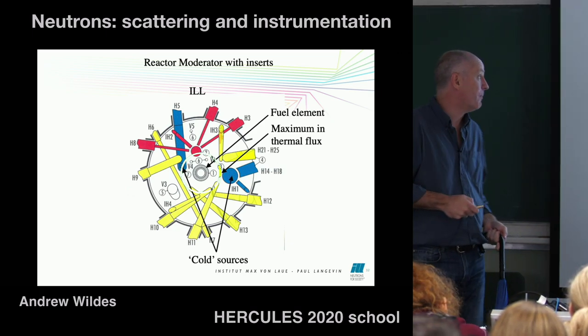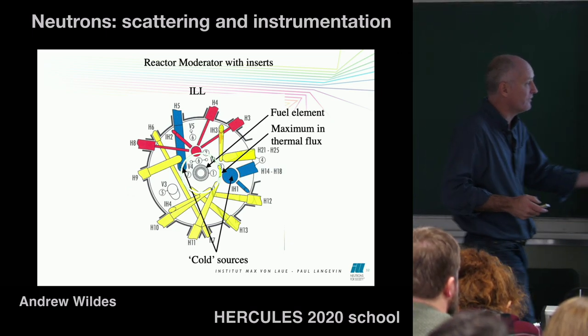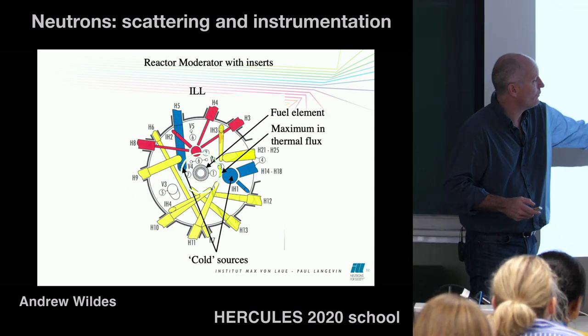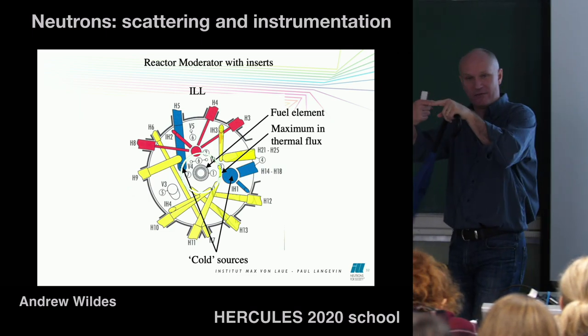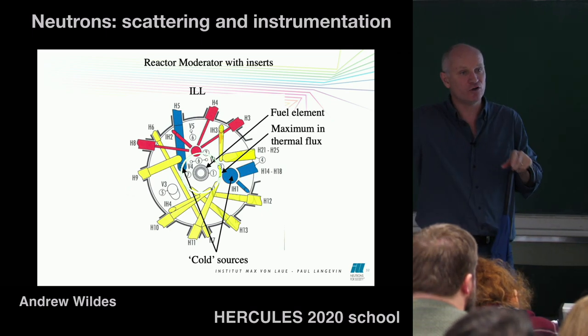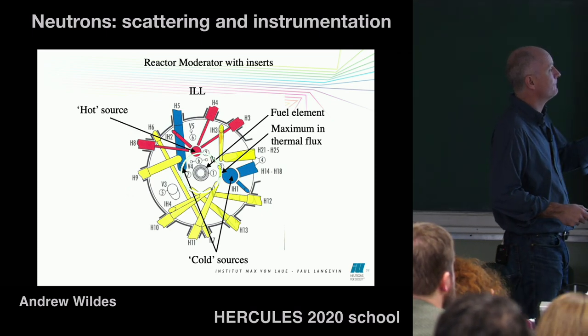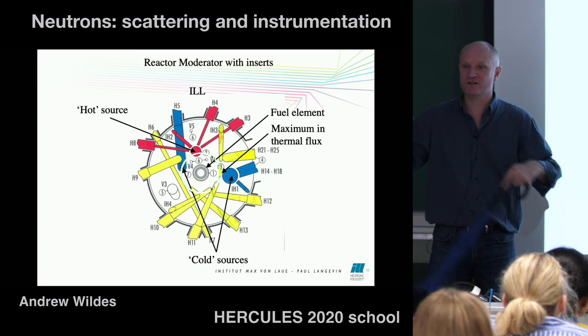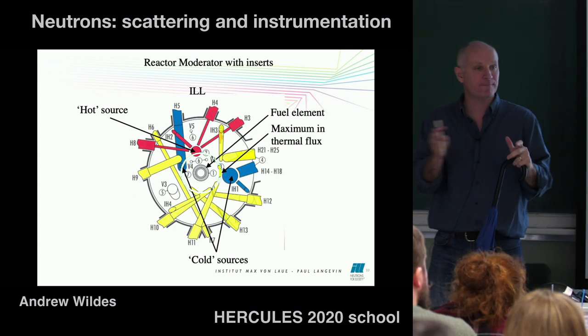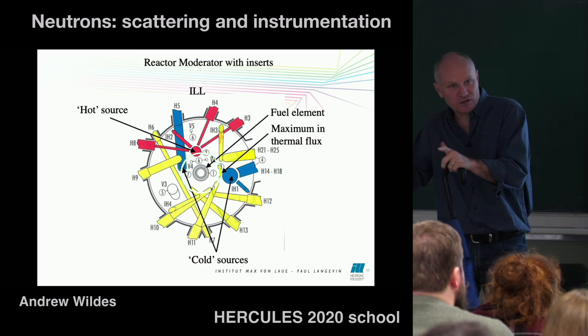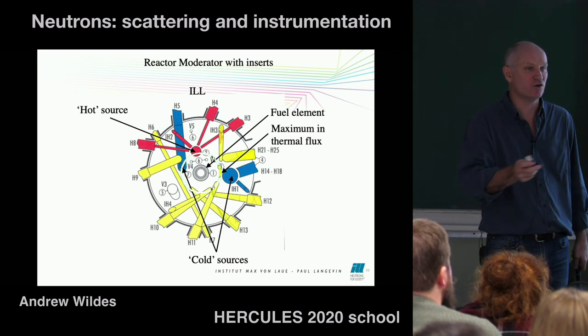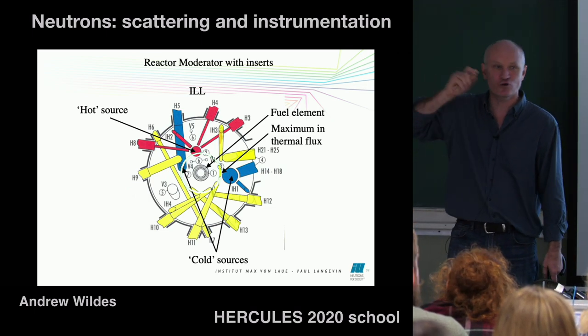And then there are a bunch of inserts. You have these two cold sources, one there and one there, and then you've got some beam tubes that point at those cold sources. They're seeing the colder neutrons come out. And you've got one hot source here. Again, you've got a bunch of these beam tubes pointing to the hot source. And that's the way that you would shift around the distribution of neutrons to be able to most efficiently do your experiment with the maximum number of good neutrons.